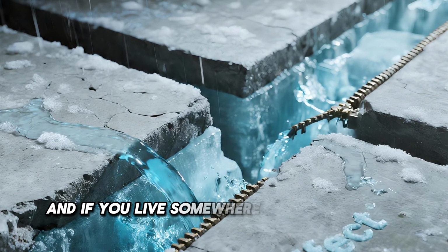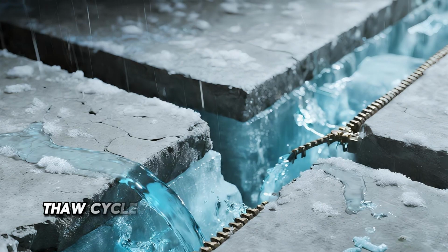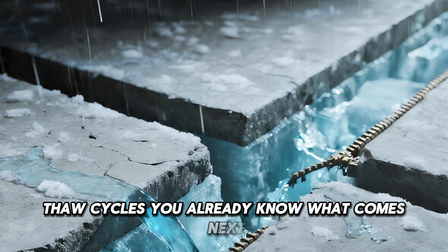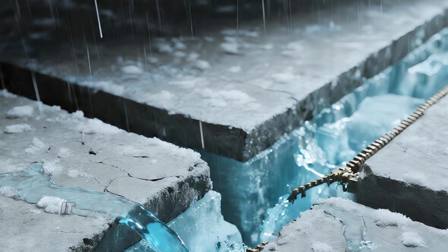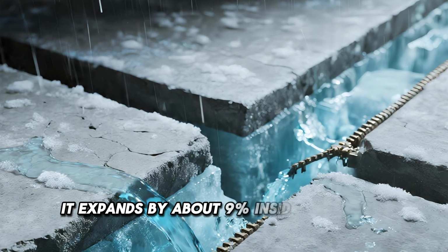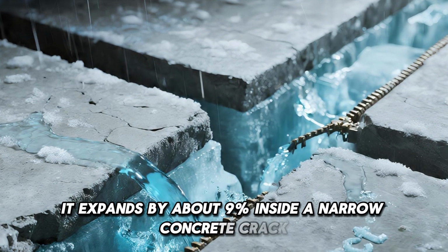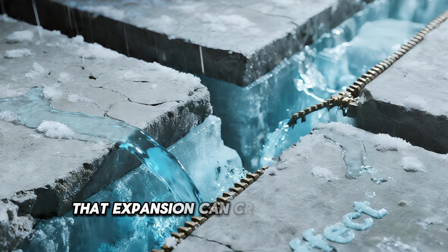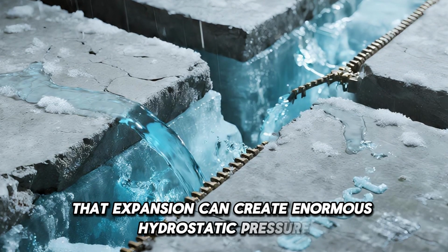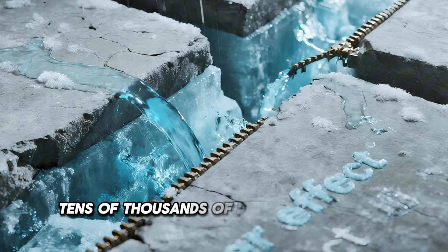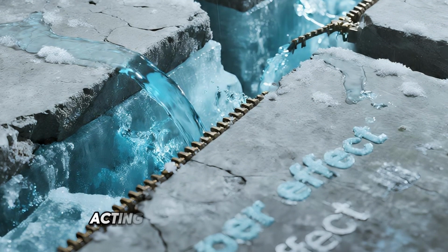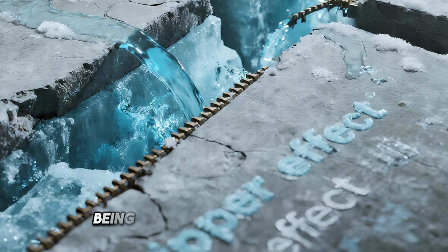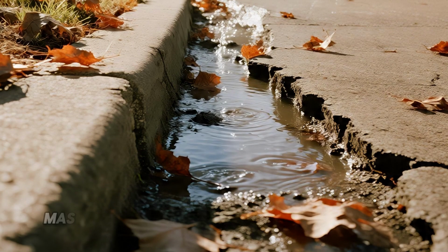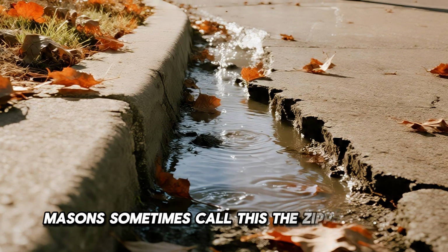And if you live somewhere that experiences freeze-thaw cycles, you already know what comes next. When water freezes, it expands by about 9%. Inside a narrow concrete crack, that expansion can create enormous hydrostatic pressure, tens of thousands of pounds per square inch, acting almost like a steel wedge being driven deeper into the slab. Masons sometimes call this the zipper effect.